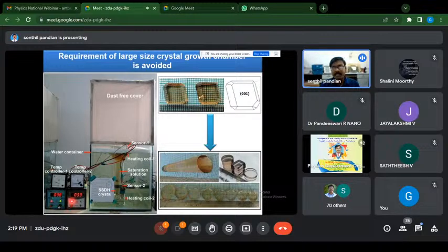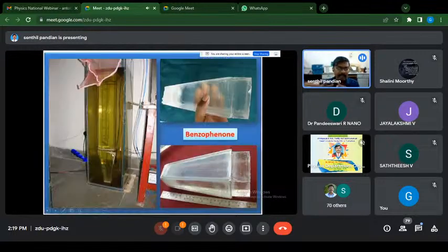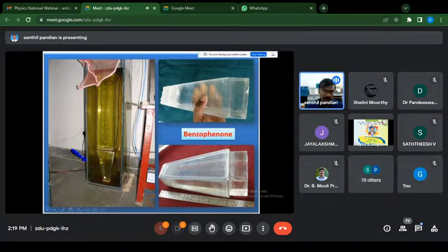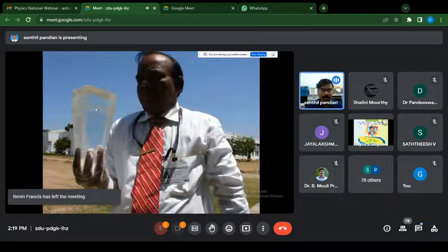This is the conventional method grown SSDH single crystal. Along its C direction, we have successfully grown this large single crystal, and these are the cut and polished wafers. Not only cylindrical shape, depending upon the shape of the crucible, any shape is possible by this SR method. The benzophenone single crystal seed crystal is mounted here. Large size benzophenone can be grown by this method using xylene as a solvent. This is the benzophenone crystal, an organic material for SHG application, and the professor is holding the organic benzophenone single crystal. This much large size single crystal is possible by this method.